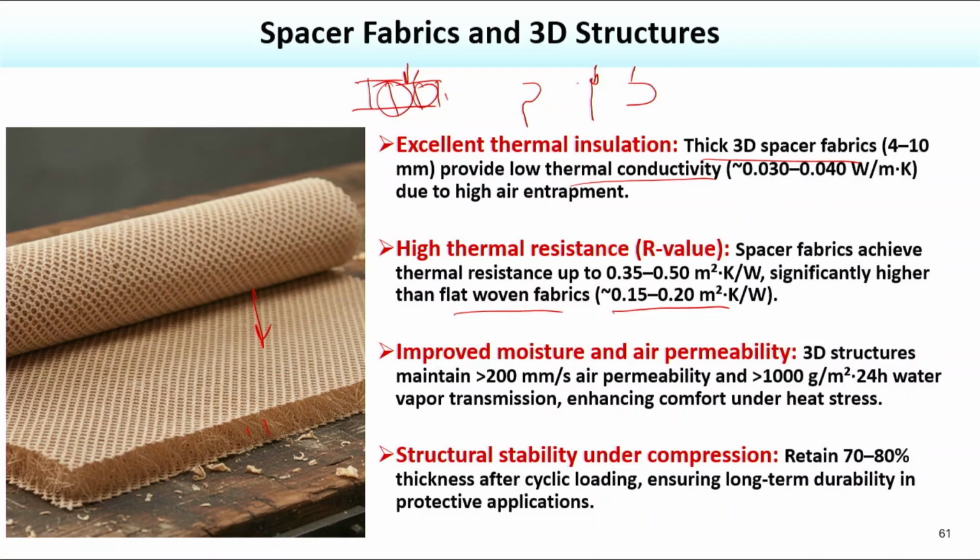That is why structural stability is very high, retaining 70 to 80% thickness after cyclic loading, which is very good for long term durability and protection.